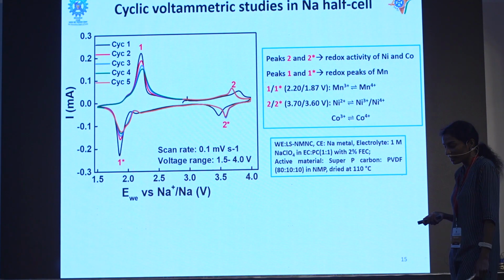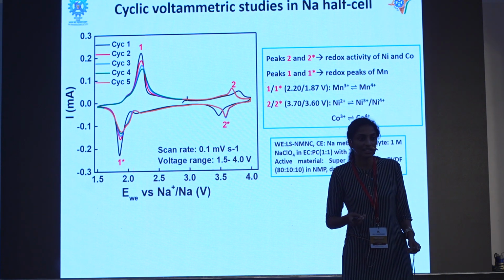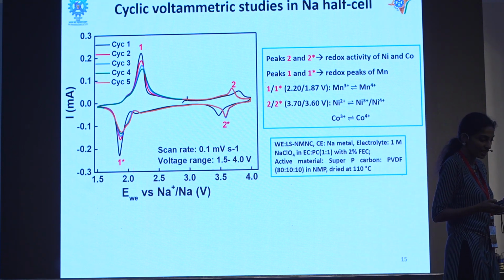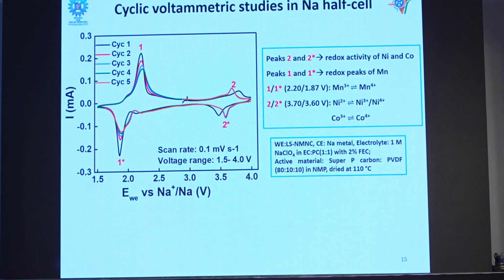Now I talked about voltage, right? Now we are getting close to the title, why voltage is important. So we did a cyclic voltammetry analysis to figure out how the oxidation of the transition metal ions is happening inside the material. And we can see that the material initially, the black curve, initially after we assemble the battery, it was about 2.9 volt. And once you charge the battery, look at the black curve, it is cycle 1.